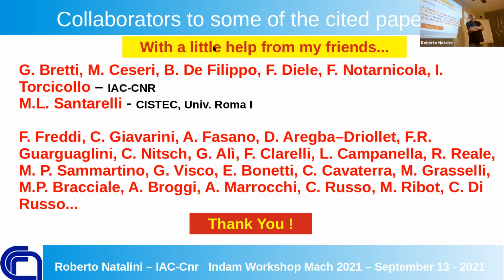Some X-ray, CT scans, or synchrotron can be used, but you cannot take monuments like the Pietà of Michelangelo and put them in the synchrotron. So usually it's very difficult to assess the state of the material. That's also one of the problems, because you cannot measure the environmental situation by sensors. So you can make a campaign in the lab and in situ, with specimens of the same material around the monuments, and try to estimate what is happening inside. You can make a hole, but you can destroy the monument.